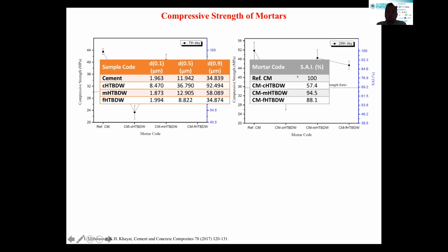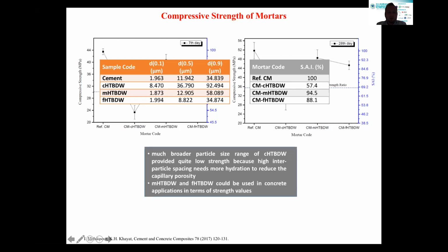So we accept 100% for the reference cement mortar, and for the coarse powder there is a reduction of the strength, and the highest value is obtained for the medium heat-treated powder. The much broader particle size range provided quite low strength, as I said before, due to the high interparticle spacing, which needs more hydration. In terms of strength values, medium and fine powder could be used in concrete applications.